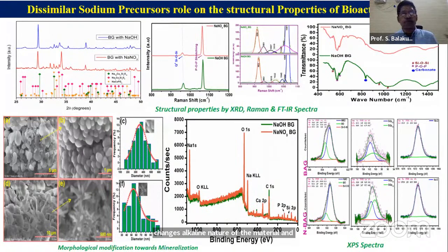So here we have used two different sodium precursors. I'm just demonstrating here: one is sodium hydroxide and the other is sodium nitrate. So we have two different results. Once you use one, you get a spherical morphology. When you use sodium nitrate, your pH levels are different and the supersaturation is different. Then obviously the supersaturation is very high, and you can see a lot of spike structures.